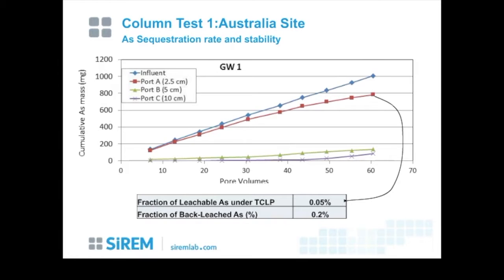We also look at the cumulative mass of arsenic going through the column, and what this plot just shows is that most of the arsenic was retained in the initial few centimeters of the column. And so you can see that the influent is the blue arsenic concentration, and port A, which is the first sampling port after 2.5 centimeters, the arsenic was there.